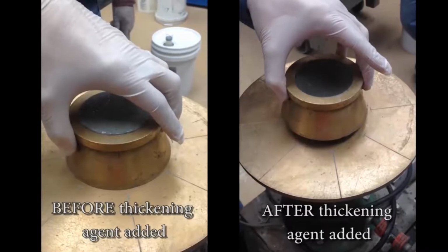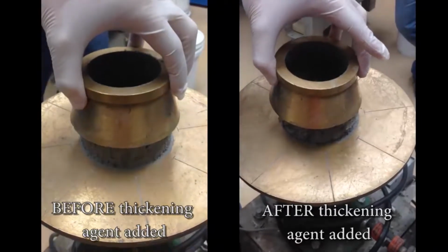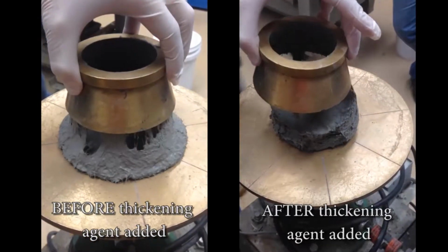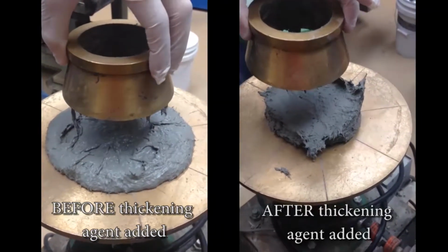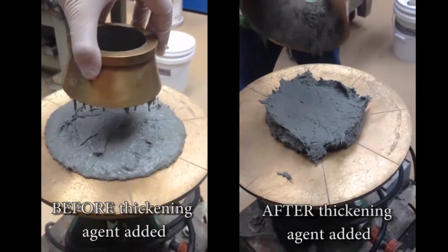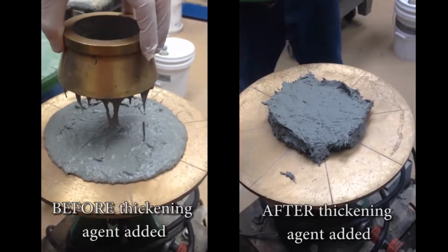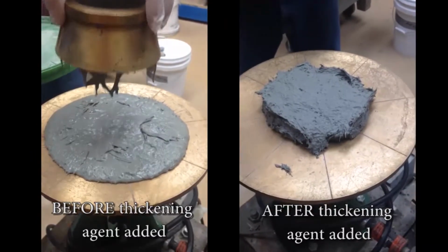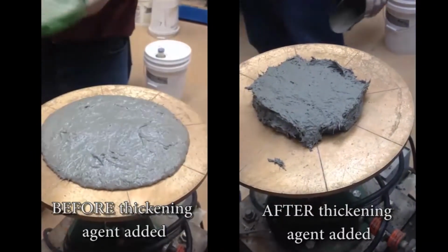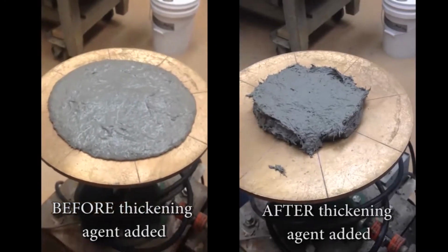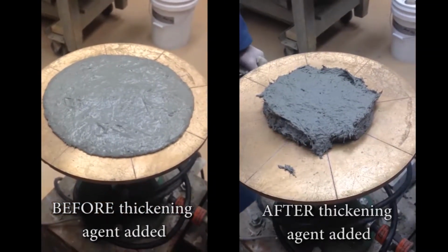This might look like, or a video, I guess. So UHPC in most typical applications is used as the one on the left. This is a self-consolidating material. But in applications where you're worried about a bridge deck that might have a super elevation, you would probably want to add what they call a thickening agent, basically to make sure that it doesn't move around too much or flow off your deck into the water below or anything like that. We call this type of behavior, that it only moves when it's being vibrated, but when you take away the vibration, it stops moving, thixotropy. So this material is thixotropic.